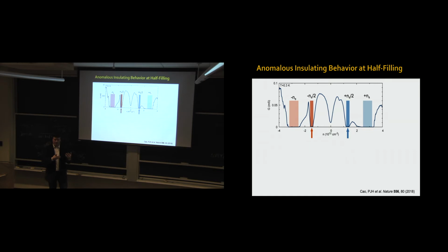There were several pieces of information that led us to conclude it's even more unusual than we thought originally. One is that this behavior only happens when you make devices where the rotation angle between the two sheets is 1.1 degrees plus or minus 0.1 degrees. You only see this insulating behavior for angles very close to 1.1. If you're 0.2 degrees away from 1.1, you do not see any of this. So it's clearly tied to this flat band condition. I'll comment on that more later.